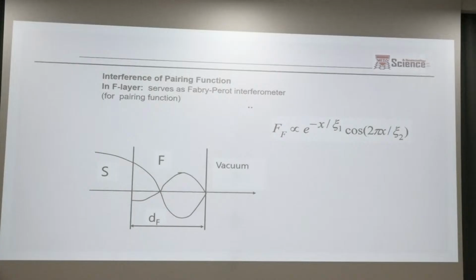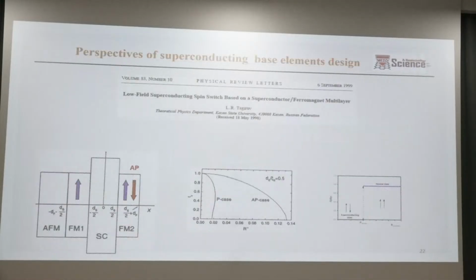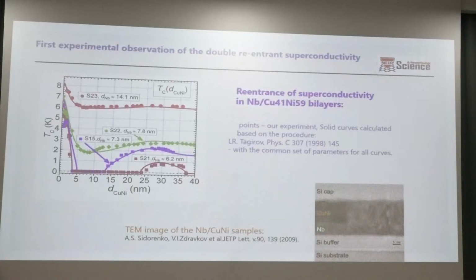And for the Cooper pair wave function, the ferromagnet layer serves like a Fabry-Pérot resonator, and there will be a maximum or minimum of critical temperature depending on the thickness of the layer. That's why if we effectively change the thickness of the layer by changing the magnetization of one layer, then we can switch from superconducting to non-superconducting state, like on the right panel. We have elaborated the technology, prepared such structures and demonstrated that it does work.